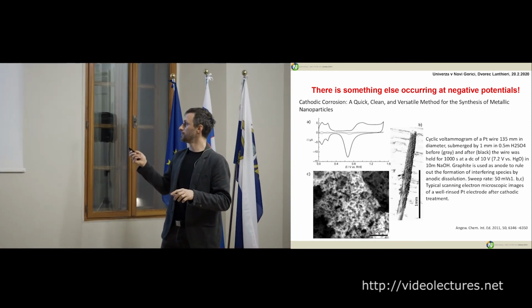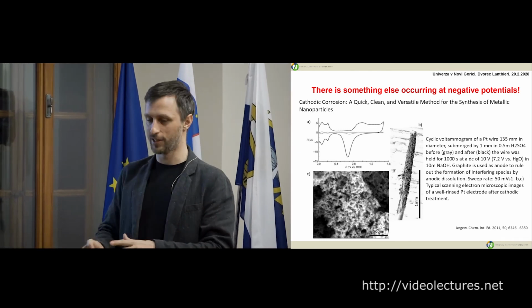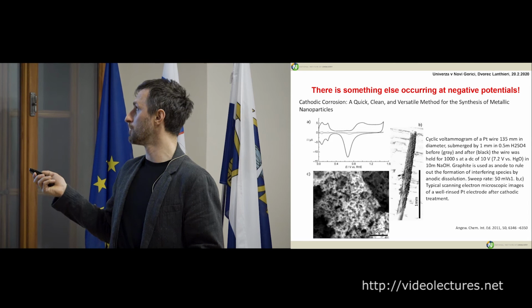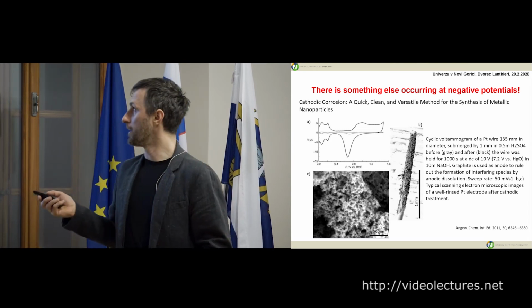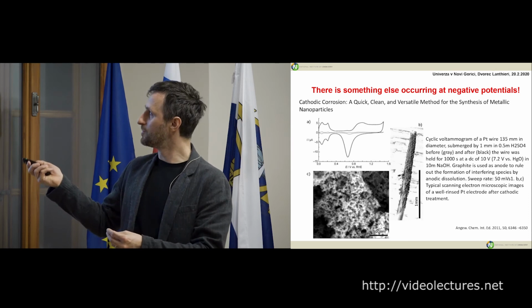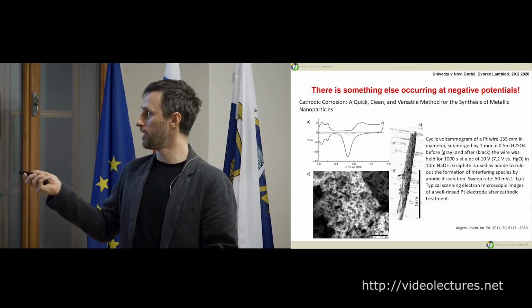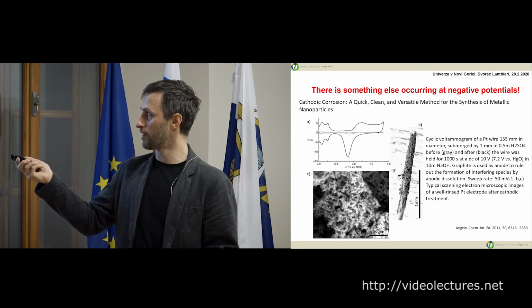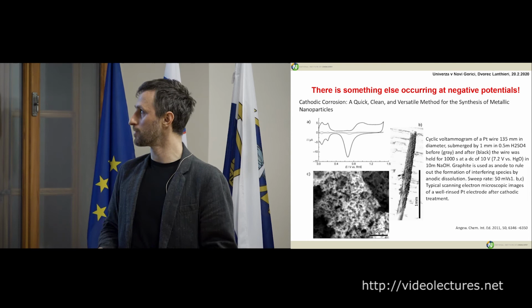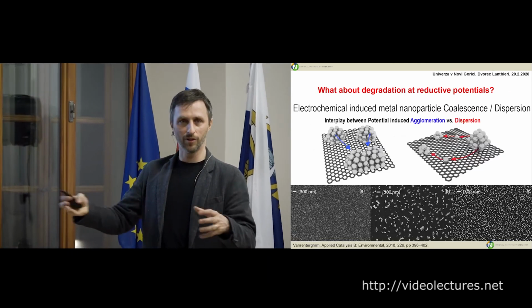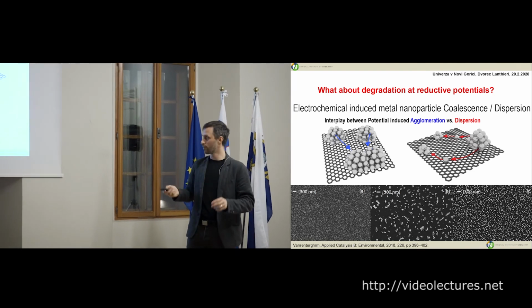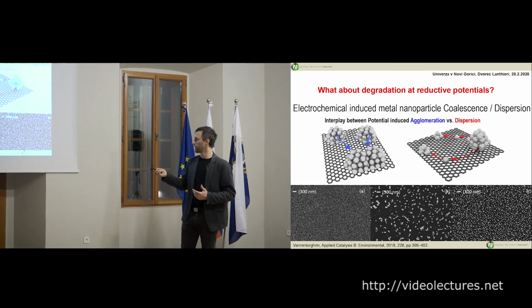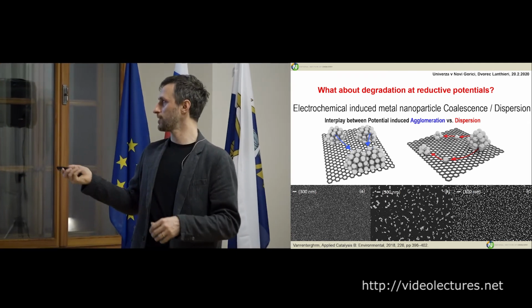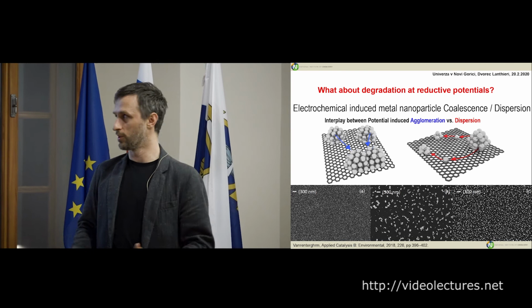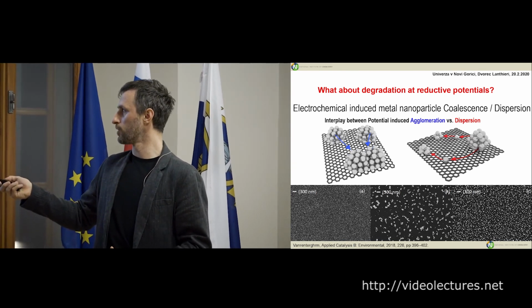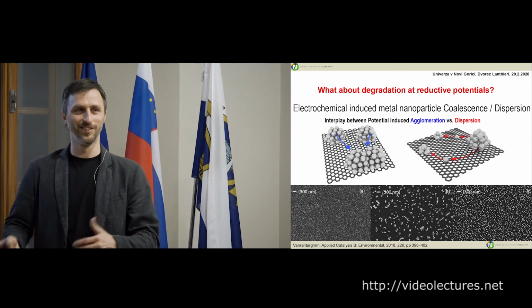There's some nice, interesting phenomena occurring in the negative potentials. You have to go to about -10 or more, and then you get this. You're making smaller particles from the wire, so you can see the surface area grows from here to here. It's called cathodic corrosion. The idea was, if we degrade it by coalescence, maybe we can reactivate it by this corrosion. And I think we were the first to actually show this. So it coalesces, and then you reactivate it by this cathodic corrosion. You go to -2 volts to degrade it, and then you go to -8 volts to reactivate it.